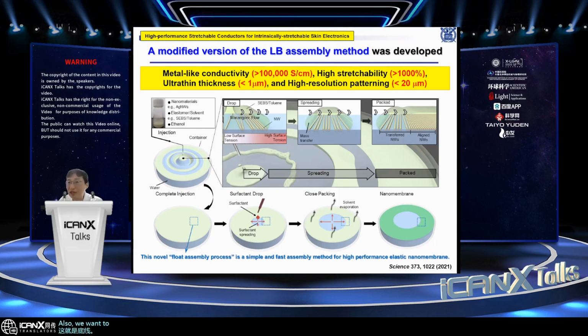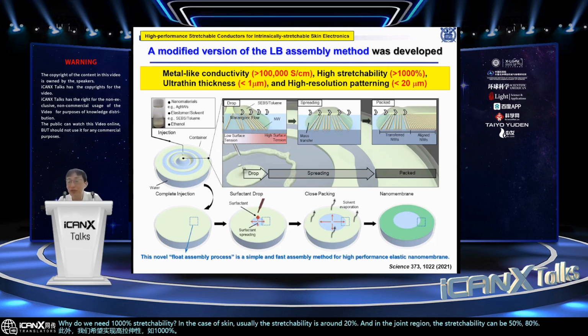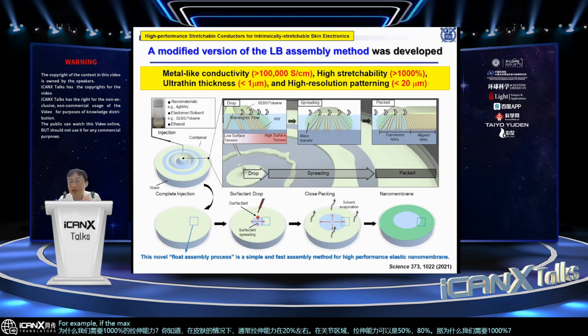Also, we want to achieve high stretchability like 1,000%. Why do we need 1,000% stretchability? In the case of skin, usually the stretchability is around 20%, and in the joint region, the stretchability can be 50% and 80%. Then why do we need 1,000%? That is related with material fatigue. For example, if the maximum stretchability is only 100%, and if we stretch the material 80% multiple times, like 1,000 times or 100,000 times, then since the maximum stretchability is only 100%, fatigue will be accumulated inside the material.